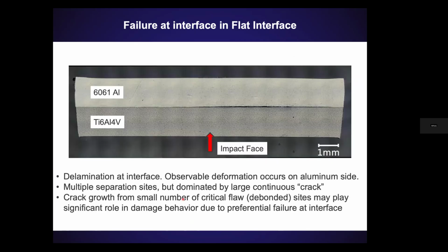In fact, when we recover our example, we do see that material fails at the interface. But this is really different than what we were seeing in MD simulations. Because in MD simulations, we're always failing on the aluminum side and never on the titanium.